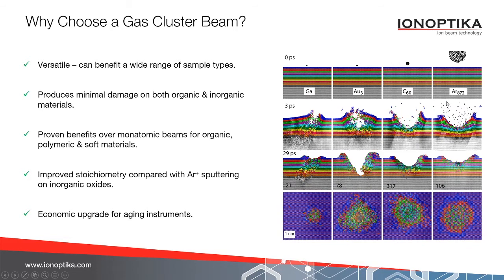So to explain why a GCIB is such a soft sputtering beam, I will use this diagram to help explain. Comparing a monatomic ion beam such as gallium, traveling at high energy, the ion beam penetrates very deeply into a sample, shown here in this illustration as different layers. So each colored layer is standing in for an atomic layer.